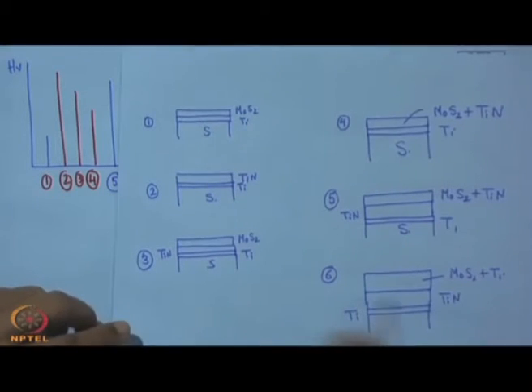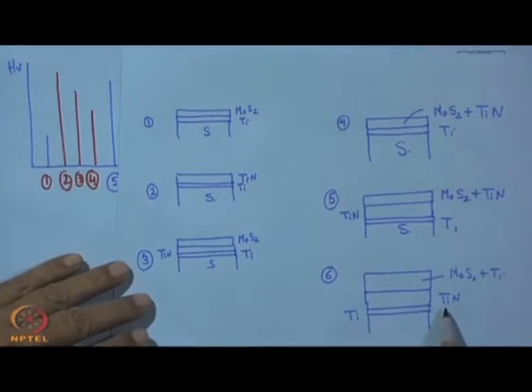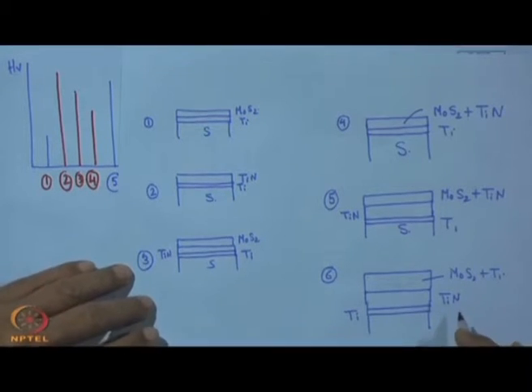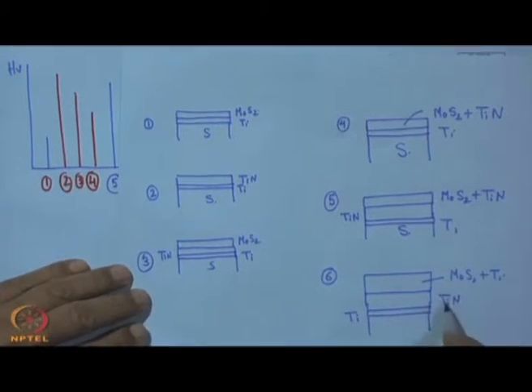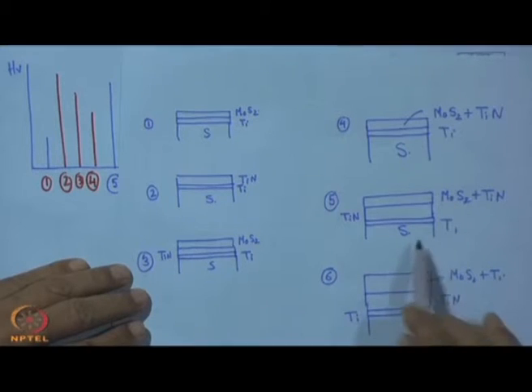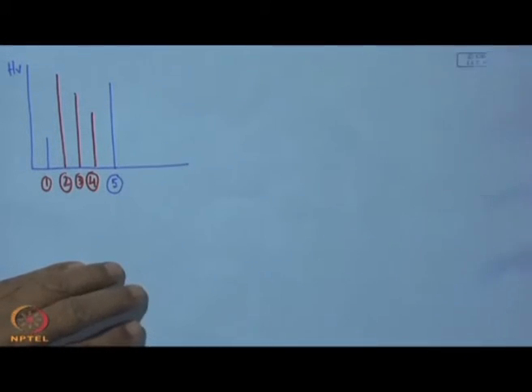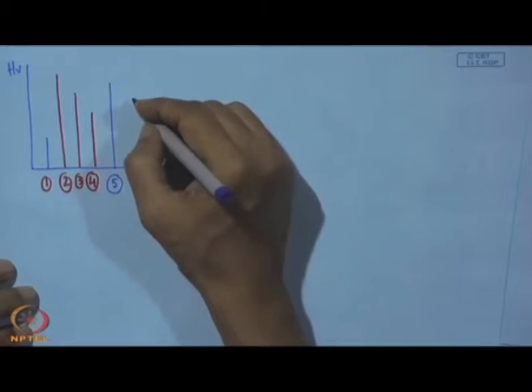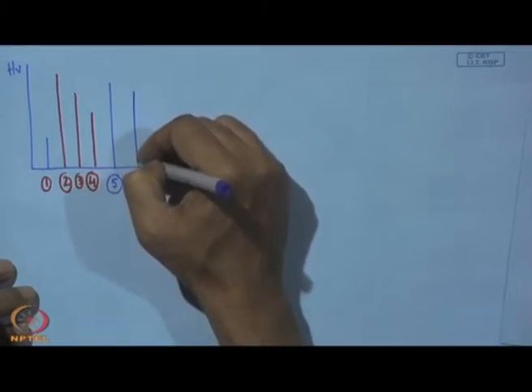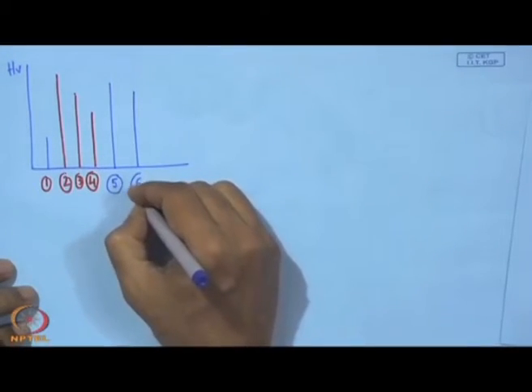And then we have this MoS2 Ti plus TiN, and this is going to be one which will give a hardness somewhere little more than this, and so it will be 6. So, it will be here, less than 5, but more than 4. So, this is the distribution of hardness.